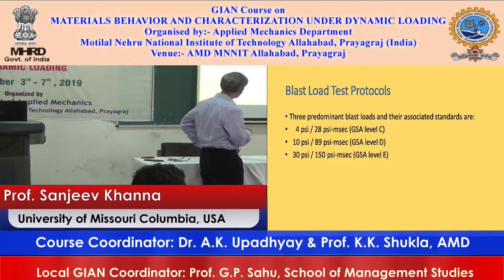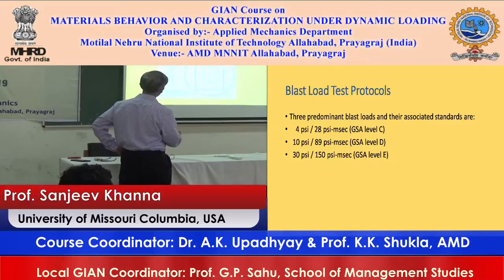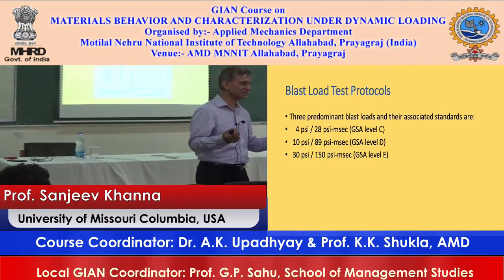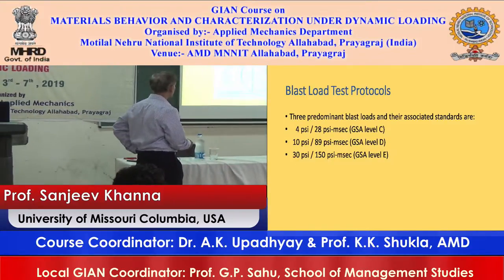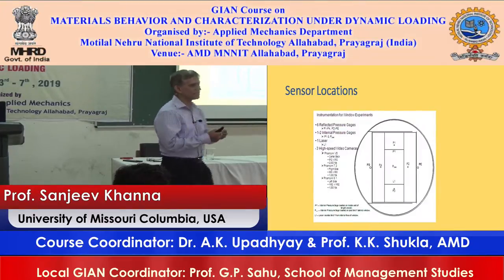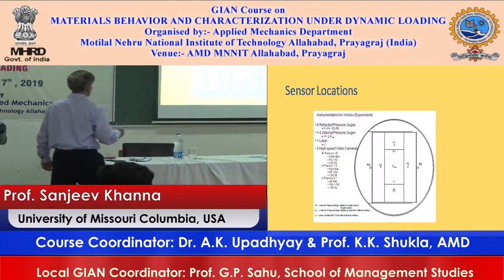So this P here, these are the five points where they were measuring the displacement. Okay. So this is the window, and this one is right at the corner in the frame. They put a transducer there to see that there should not be too much movement at the end of the window. Most of the movement should be in the glass portion and not in the frame. And then our main interest was in the center one. This was done using an LVDT, linear variable differential transformer. As I showed you in the simulation yesterday, we were trying to match our results numerically with this center point deflection.